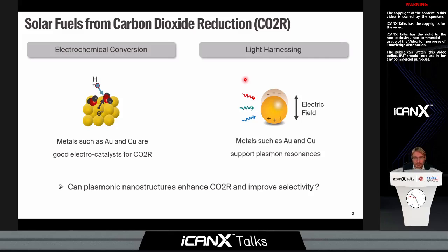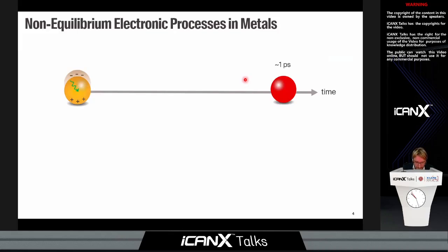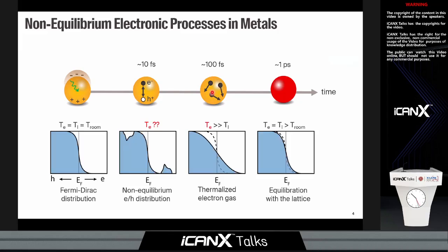The thing is that we have to go back and analyze the processes that occur in a metal during and following photon absorption. Typically, we used to think of metals as purely lossy materials where all of the energy of the photon is dissipated into heat. However, when we look at this process on a time scale, there are actually two intermediate steps which are quite interesting. From the dephasing of the plasmon and the photon absorption, quite promptly we can generate an electron hole pair, and it's only on a hundreds of femtoseconds time scale that these carriers will collide with each other and thermalize.